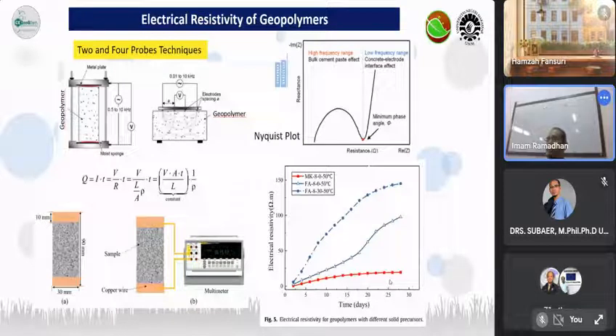You can use 2 or 4 probe techniques in order to assess the electrical resistivity of geopolymer, by using alternating current with a very low frequency to a very high frequency, say, for example, from 0.1 hertz to 100 kilohertz. Then you can have a very nice Nyquist plot that displays the conductivity mechanism of the electrons of your materials,